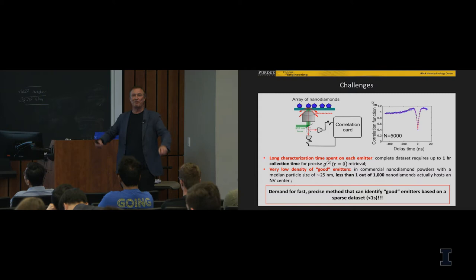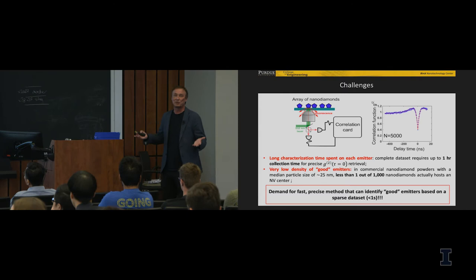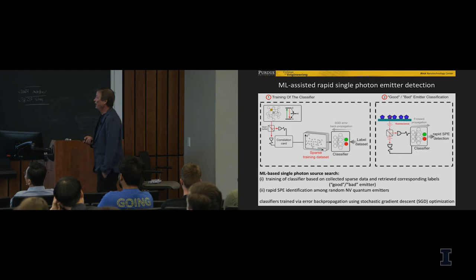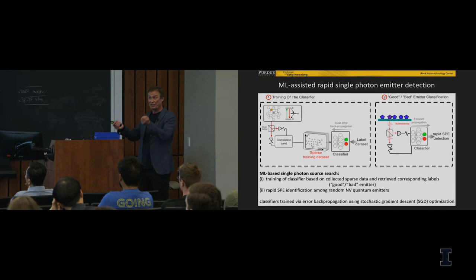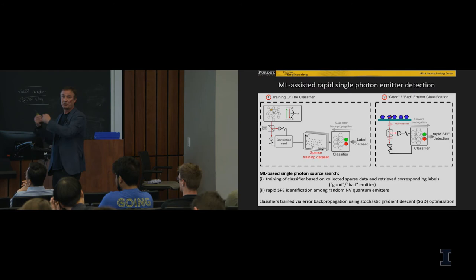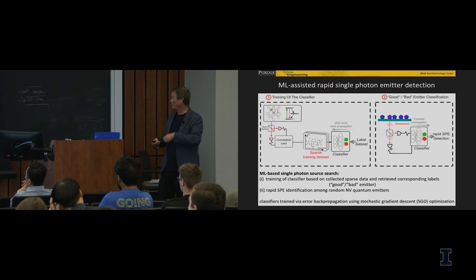It's simply impossible, basically. Let's put it this way. Unless you speed it up significantly, it becomes simply impossible. And the idea is simple. You basically train your classifier, and in this case, you're dealing with a classifier for single or not single photon source, by using this sparse data collected within 1 second or so, and retrieve corresponding labels by doing these complete experiments. And you could train with 15 or so nanodiamonds by using this 1 second experiment your neural network, and eventually you could say whether it's good or not in a very fast fashion.